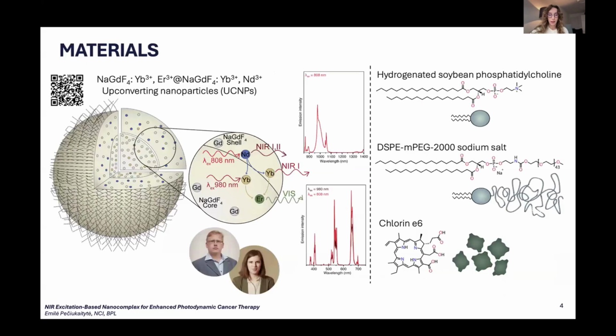upconverting nanoparticles were synthesized by Dr. Vaidas Klimkevičius and PhD student Eglė Žirskytė. The nanoparticles consisted of sodium gadolinium fluoride doped with erbium, ytterbium, and neodymium ions. This combination of lanthanides allows excitation with both 808 and 980 nanometer laser light, providing flexibility and reduced risk of photothermal effects. For surface modification, we used phospholipids, phosphatidylcholine and polyethylene glycol, or PEG, conjugated phosphoethanolamine. These phospholipids were combined in 3 different molar ratios, and chlorin e6 served as the photosensitizer.